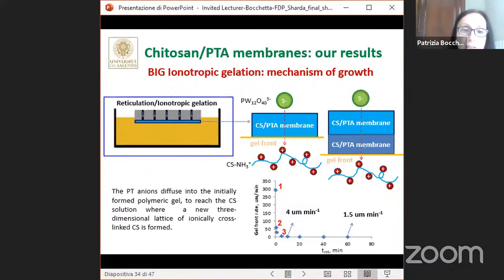phosphotungstate anions diffuse into the initially formed polymeric gel and reach the chitosan solution, forming a new three-dimensional lattice of chitosan. Second step, the gelation front rate drastically decreased, indicating that a new process controls the gelation kinetics. Finally, at about 20 minutes of ionotropic gelation, the gelation front rate became insignificant. So the membrane does not grow anymore.